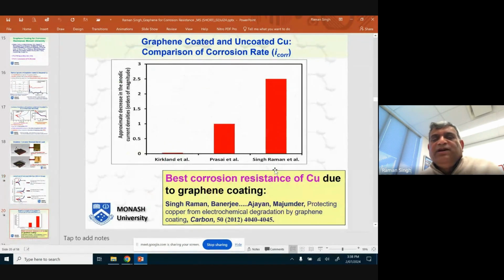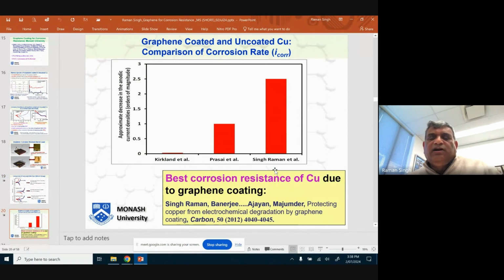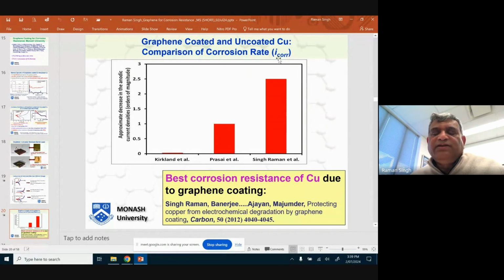Around the same time, a few other people were also working on this project. So as I said, graphene got the Nobel Prize in 2010. We started to work on this in 2011, and we published a paper in 2012. And you can see that we were getting 2 orders of magnitude improvement in corrosion resistance, whereas one group from the United States was getting just less than an order of magnitude improvement, and another group was getting no improvement at all. So we were all working with graphene-coated copper and doing tests in a corrosive environment. We were getting 2 orders, others were getting far less. And it's very good that we can claim, oh, we were getting the best results.